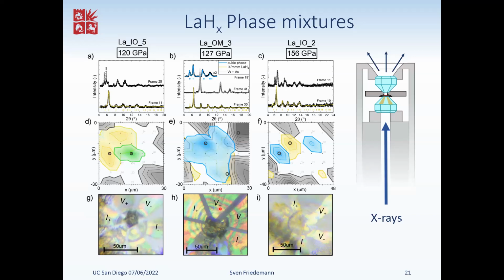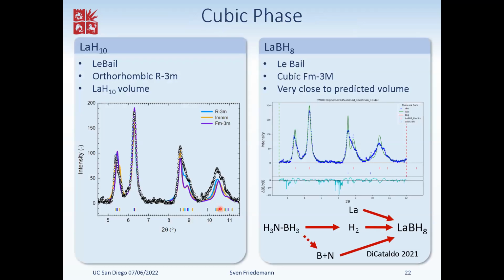And also here, regarding what you asked earlier about contamination, having this ammonia borane around gives you in fact a plausible route to yet another phase. Namely, you've got some boron available, which could form lanthanum boron H8, which is indeed predicted to be stable, predicted to be a cubic phase, and predicted to have lattice constants very close to the cubic X-ray pattern that we observe. So it's plausible that this one is present. And in fact, it is predicted to have a TC of the order of 100 Kelvin. We observe 70, 80 Kelvin.